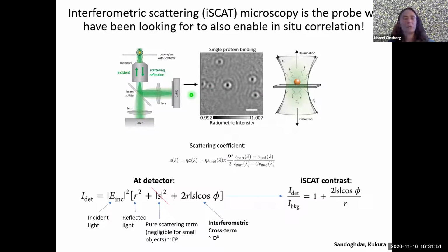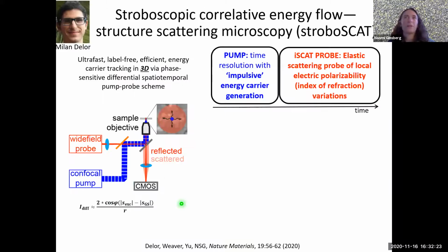And the general way that it works is that light illuminates this sample through the microscope objective, and the scattered light from the particle is collected and interfered with a sort of local oscillator, a reflection, for example, off of a sample substrate interface and detected on a camera. Okay, so it's very, very sensitive. It really allows you to see the scattered light much better than, for example, in dark field microscopy. So that is the probe that we are interested to use in our experiments.